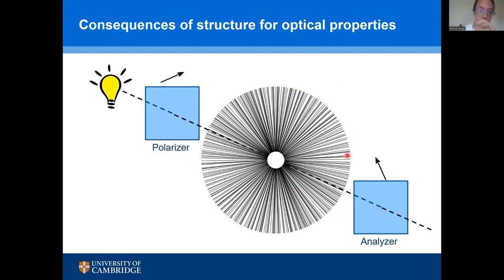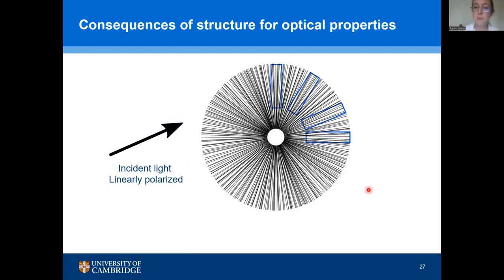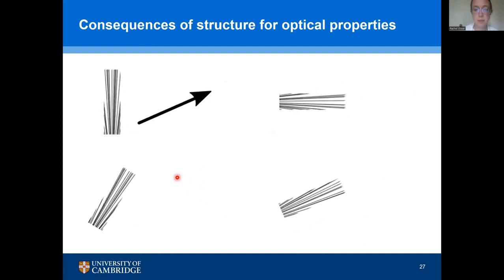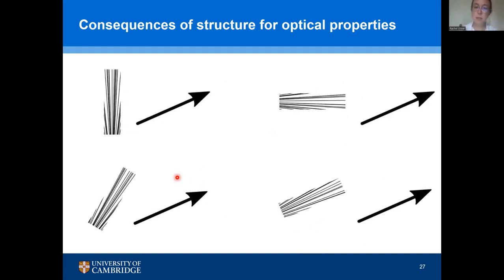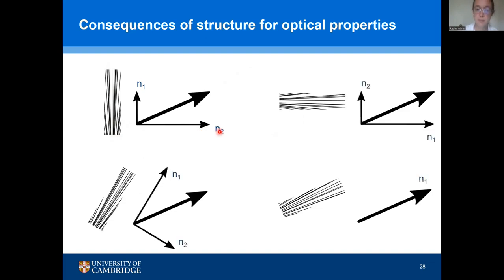If my slide will move on. So when we look at that in the polarized light microscope, what do we expect to see? Well, I'm just going to take four exemplar directions here and consider what happens to them if we've got light along the direction I'm showing on the slide, polarized. The polarized light experiences the refractive indices differently depending on what angle it finds itself to them. We'll have a low refractive index, we think, along the pores and a high refractive index across the pores.